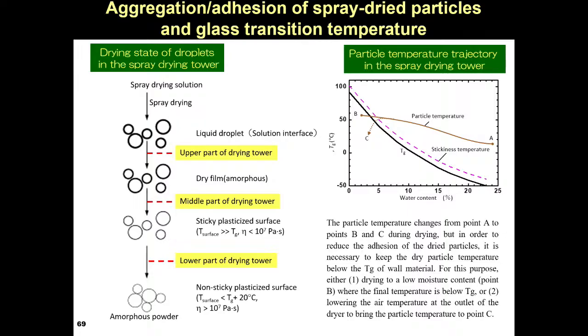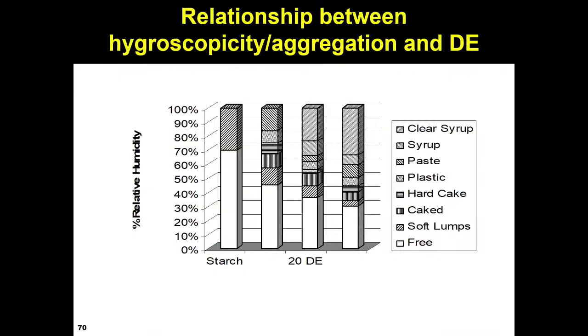Therefore, this is some particle temperature trajectory in the spray dryer. The solid line shows the glass transition temperature of the compound. The red line is the product temperature. After spray drying, the powder should be below the glass transition temperature. Above the glass transition temperature, we cannot get the powder. The glass transition temperature depends on the material. So, for example, this y-axis, the relative humidity, is for some kinds of sugars, starch, dextrose. This is dextrose, maltodextrin.